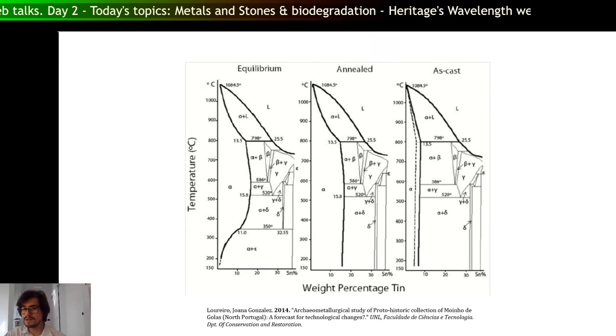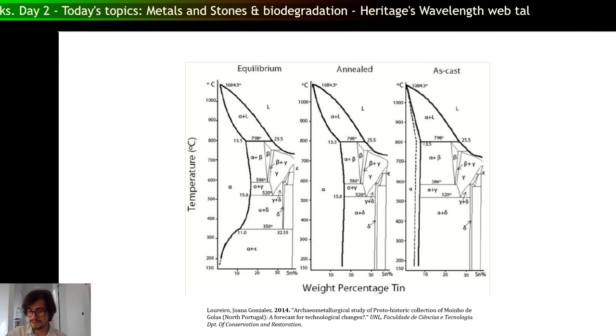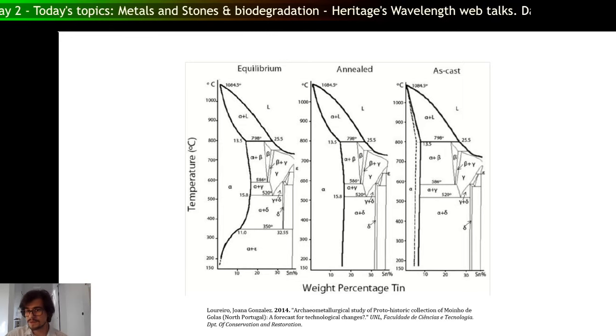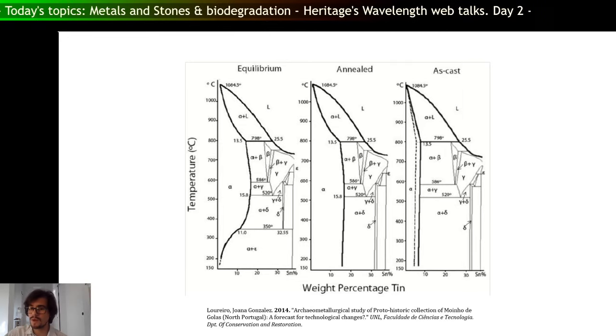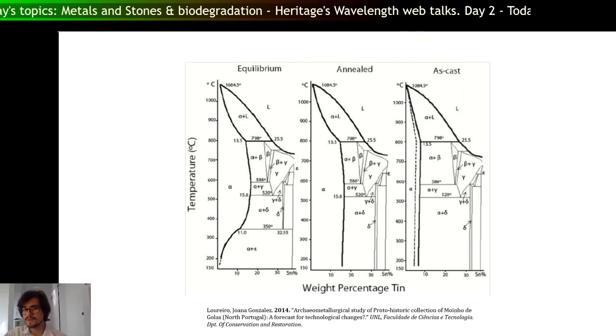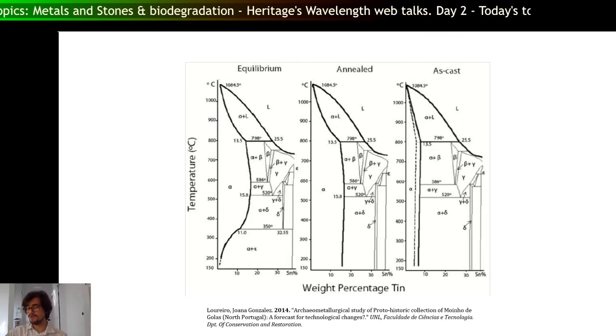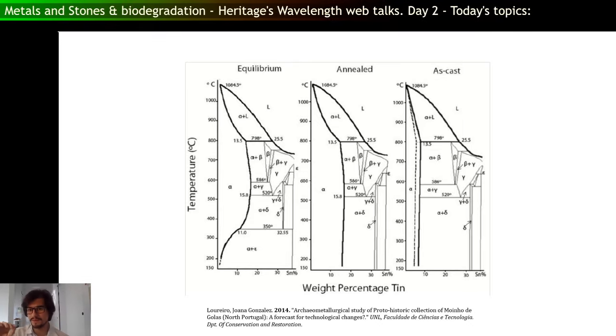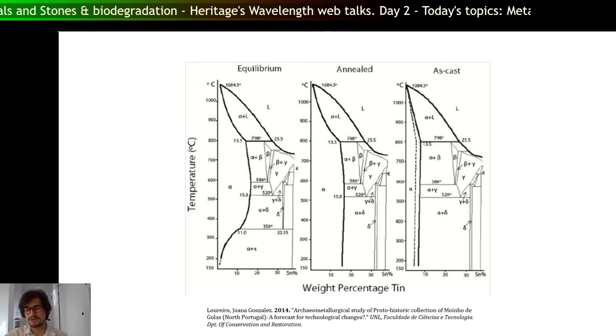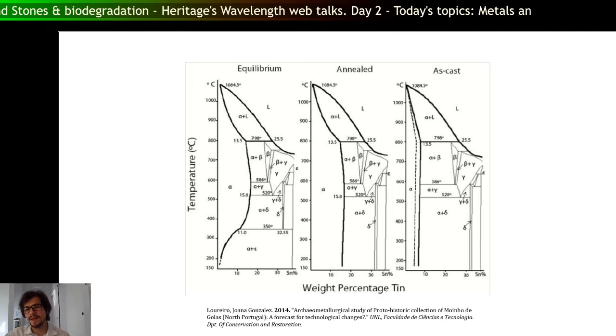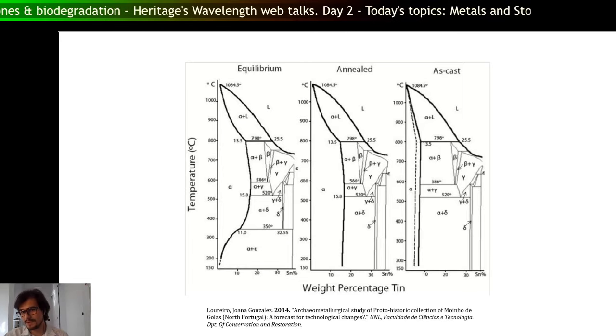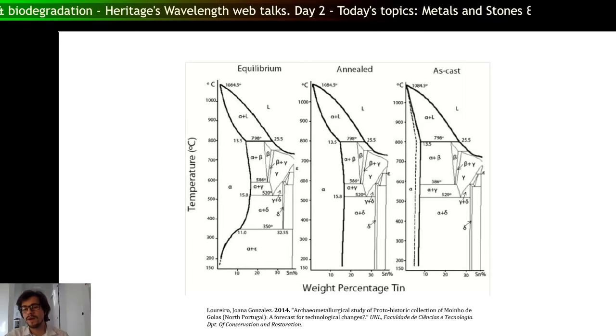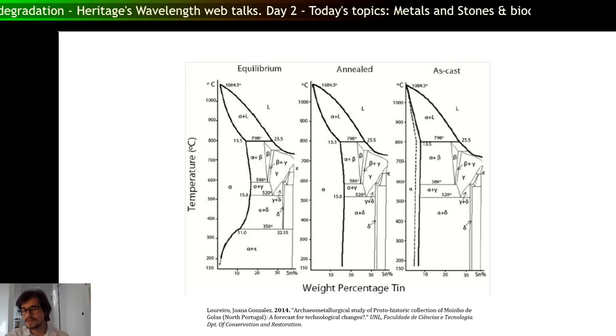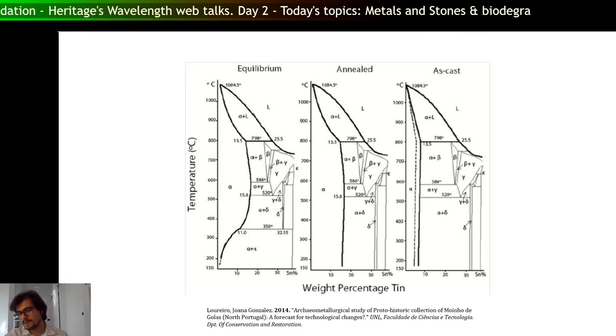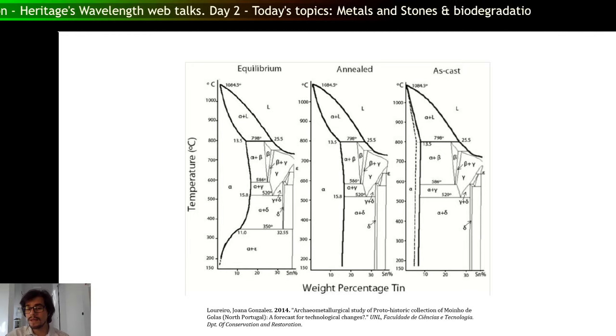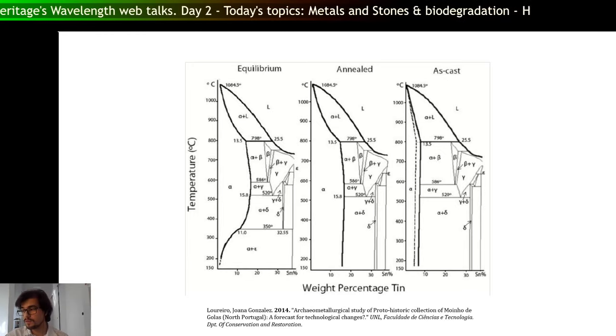If you do not anneal it, with the same metal, with 10% of tin, at the end of the process you will notice that there is one extra phase here that shouldn't be there if you had annealed it. So when you look under the microscope, the metallography, the crystalline structure of your metal, you can tell, if you did the chemical analysis before, whether that metal was annealed, how it was annealed, if it was at all. So you can attribute certain characteristics to different workshops.